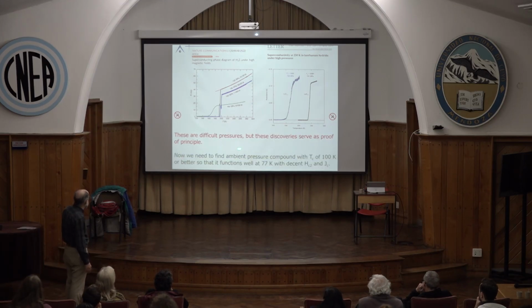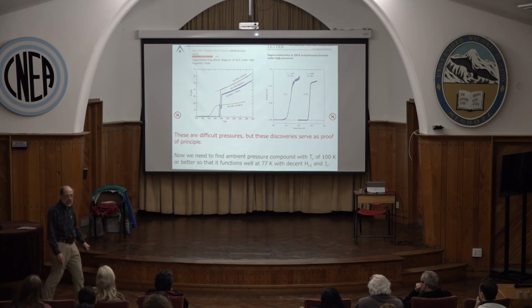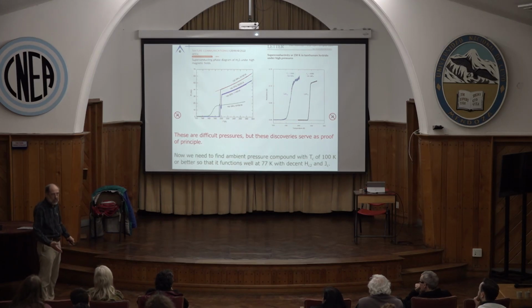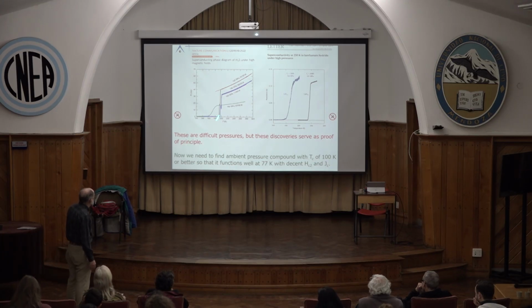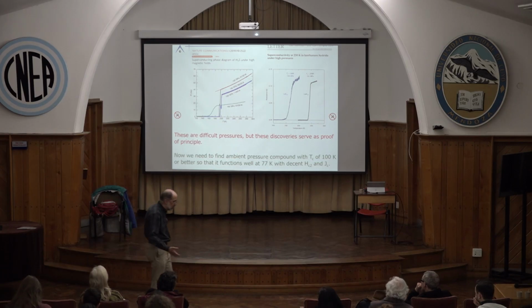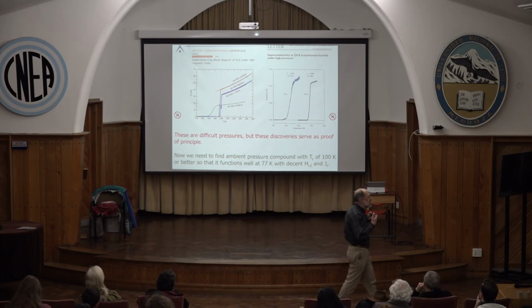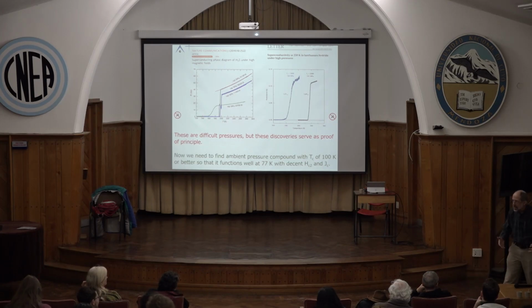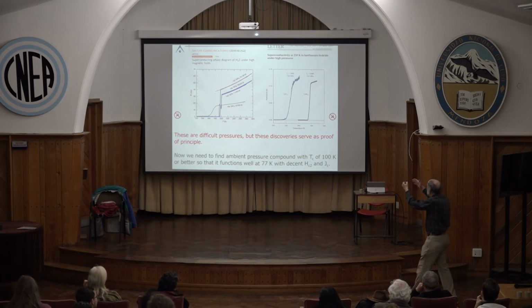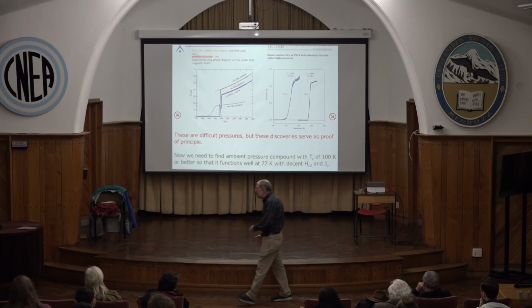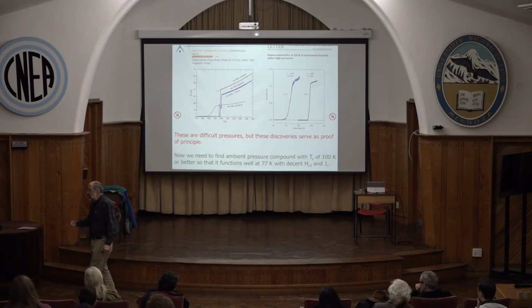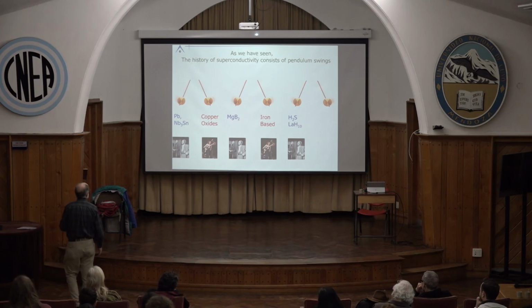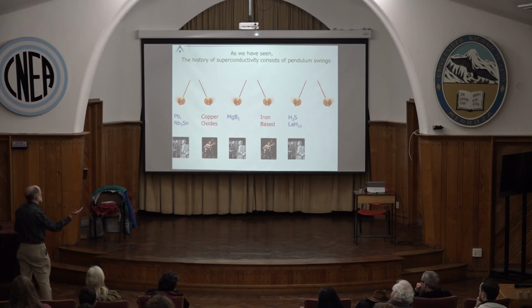Now, these are obscenely high pressures. A gigapascal is 10,000 atmospheres. So we're over 1 million atmospheres pressure. This is not practical, but it's proof of principle. These are thought to be old school BCS phonon-mediated superconductors. This is motivational because it means that maybe we can find other old school phonon-mediated superconductors that get us above 77 Kelvin, and then we hopefully won't have the problems we had with the cuprates. But this is one of the areas in superconductivity. It's exciting, but the pendulum is still swinging.